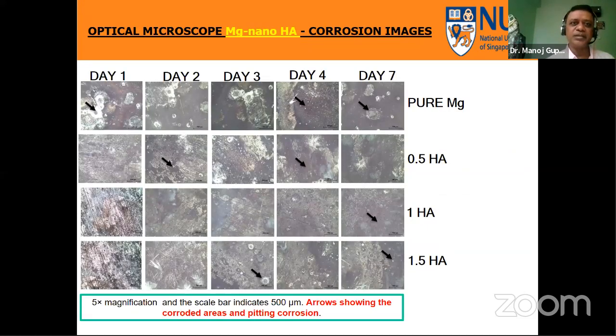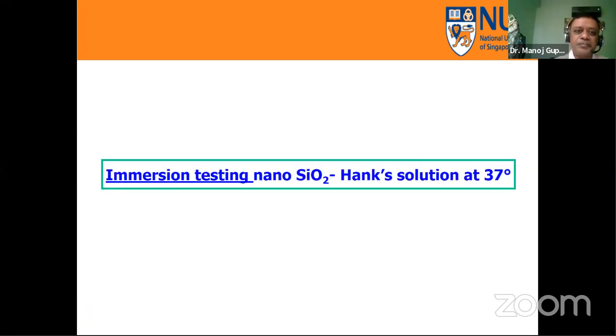We also looked at the optical microscope to see, more as an academic interest, how the corrosion takes place if it happens. Like other studies done by other researchers, we found that pitting corrosion is the main form of corrosion which affects the degradation of this material, whether it's nano HA or nano SiO2 material.